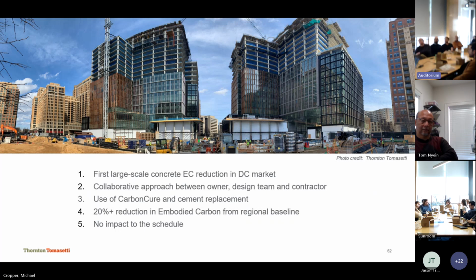That 5,000 PSI mix would be at 6,000 PSI in 3 days. And by the time we hit 28 days, it would be at 9,000 PSI. So I slept really well as a structural engineer because we were getting almost double the strength that we asked for, because the mixes ran hot. They would just use 100% cement, no problem. Don't want to risk not being able to stress the tendons on that third day, and don't want to risk the cycle times of the floors.